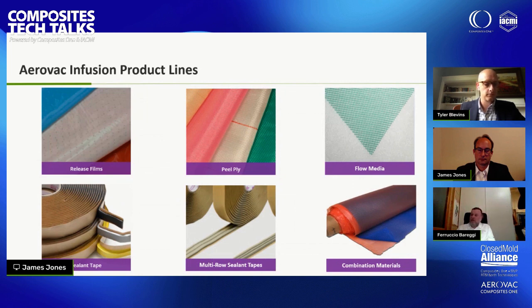Sealant tape is also an important part of the job, because it's the material that grants the vacuum tightness between the mold and the vacuum bag. There are different grades of sealant tape that differ in terms of tackiness at room temperature or maximum temperature withstanding. An improved application is also the possibility to have the sealant tape in a twin parallel format, so as to improve the application time on the perimeter of the flange.